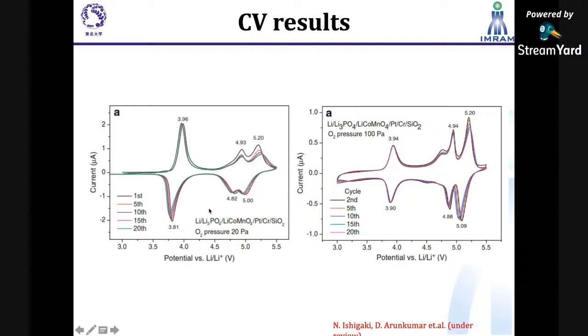However, we changed the experimental condition. We increased the oxygen partial pressure from 20 Pascal to 100 Pascal during the deposition, and this led to an increase in the cobalt redox capacity, and we could achieve 50% of the cobalt capacity, but still the capacity in the 4 volt region, the manganese redox reaction, could not be completely removed. So we are now working to decrease the manganese capacity and have the capacity only in the cobalt region. This 5 volt class all solid state battery is under development, and we are yet to publish these results.